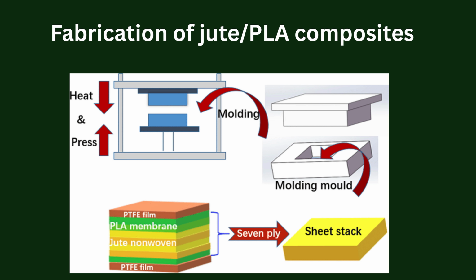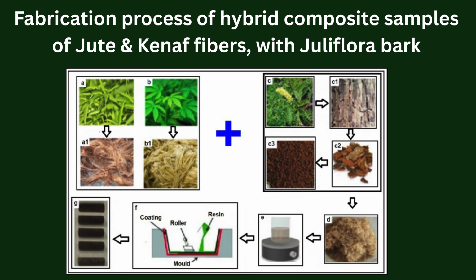Optimized processing conditions, for example, 12% sodium hydroxide treatment, 8-hour immersion, 210 degrees Celsius processing, enhance composite properties. Other bio-based matrices include biodegradable polyesters, such as Biopol, soy-based resins, and bio-epoxy systems. Hybrid jute composites. Hybrid composites combine jute with other fibers to improve performance and overcome inherent limitations.